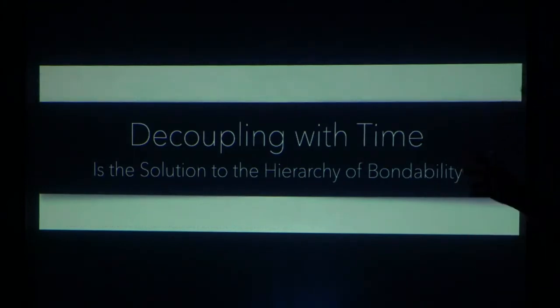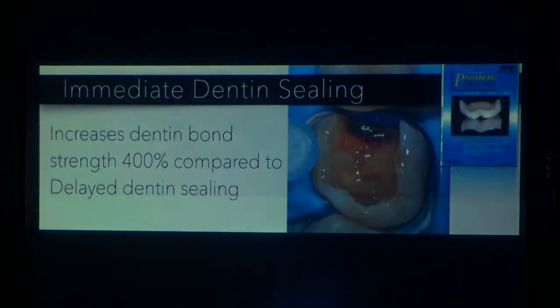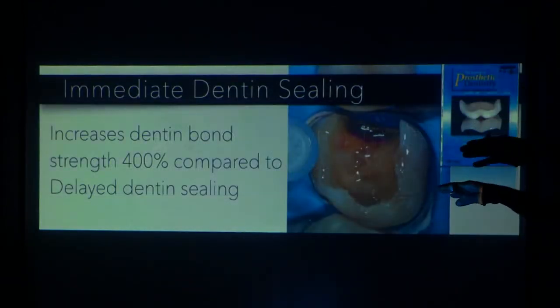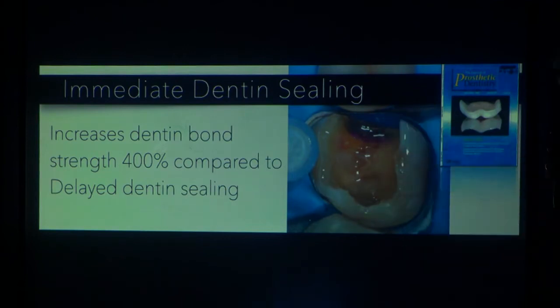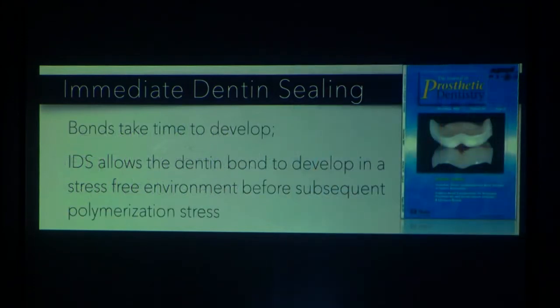Each of these techniques take time to do. So the time that it takes to do these five protocols is the key. So decoupling with time, it is the solution to the hierarchy of bondability, because once you do your immediate dentin sealing, it will give you 400% bond strength compared to trying to cement your onlay or your inlay at the same time that you bond it. So the bonds take time to develop. Immediate dentin sealing allows the dentin bond to develop in a stress-free environment before subsequent polymerization stresses.